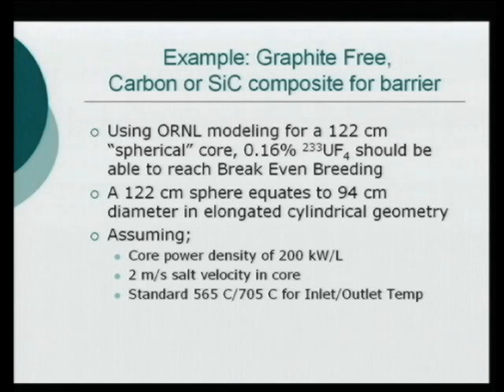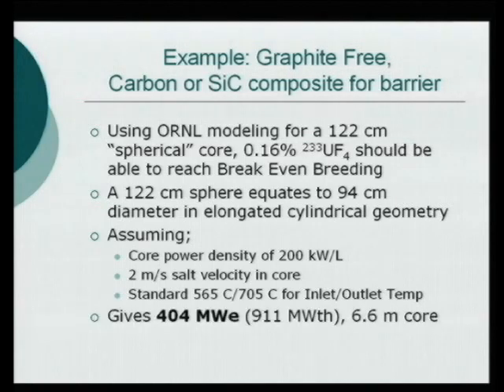And if you put in the basic power densities, actually these are quite conservative numbers, 200 kilowatts per liter, fairly slow salt speed, 2 meters per second, typical inlet and outlet temperatures, a 6.6 meter long core gives you over 400 megawatts electrical just there. And there are also other ways that give you larger diameters. And that would be, for the same length, more power.